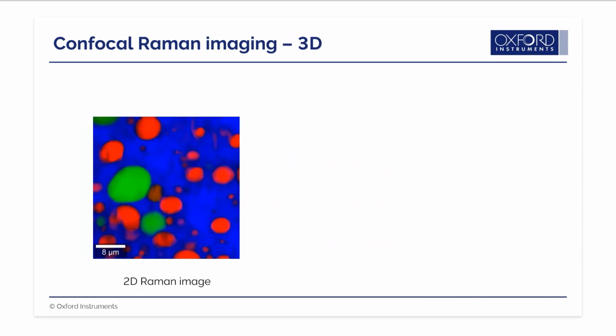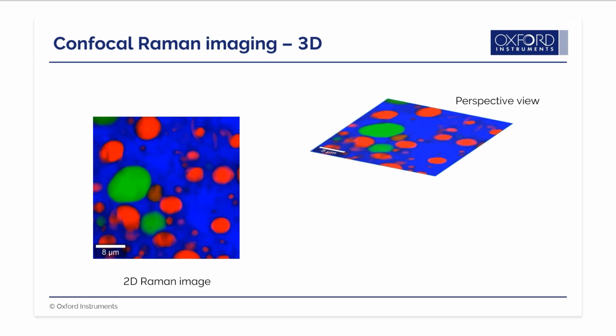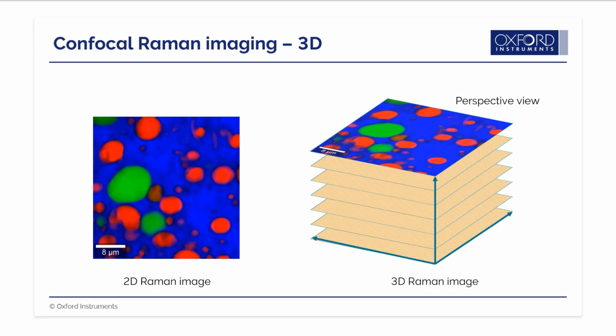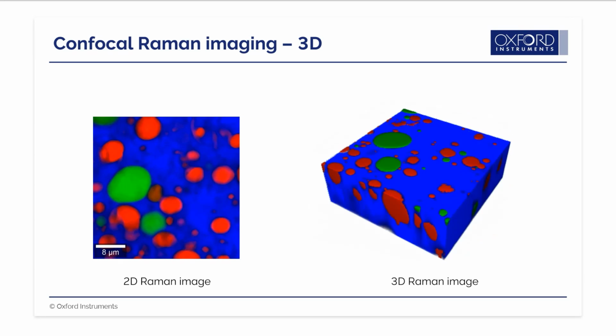If the sample is transparent for the laser, we can measure also high-quality 3D images with high resolution and speed. To obtain 3D Raman images, we simply measure a stack of 2D images pixel by pixel, line by line, and layer by layer. And by doing so, we obtain the Raman information of a full 3D Raman volume.